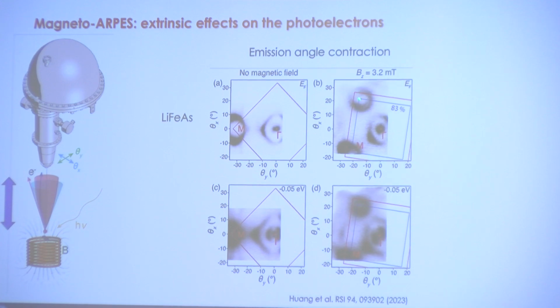The second effect we see is we measured on the iron pnictide, and you can see the rotation first, but there's also a contraction of the emission angle. So this is a natural photoemission cone, but the electrons that we measure under the field are contracted. I don't want to go into too much detail about why this is, but if you're interested, you can read this. But this is another thing that's easily manageable in our data analysis.